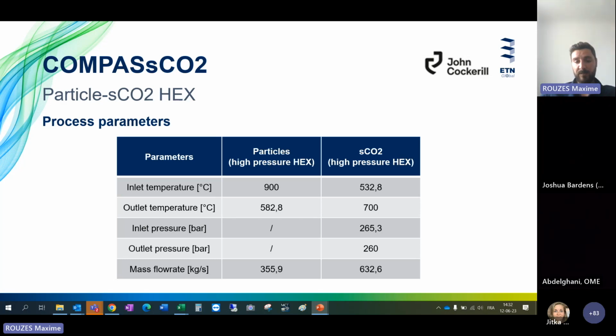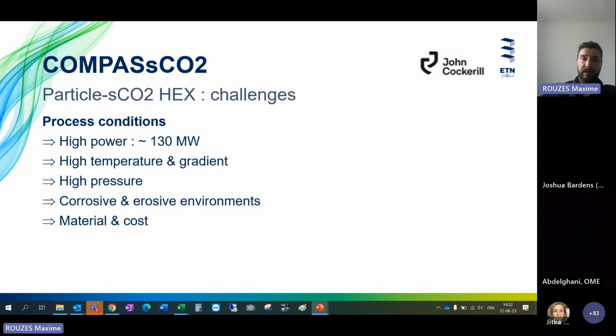In this case, the flow rates are quite important because the power is around 130 megawatts. So this is mainly the kind of environment that we have for designing the heat exchanger: high power, high temperatures, but also high gradients and high pressure. And if you combine sCO2 and solid particles, you have a corrosive environment on one side and an erosive environment on the other side of the tube. So all that leads to the fact that the selection of material and the cost linked to that will be one of the key parameters for the design.